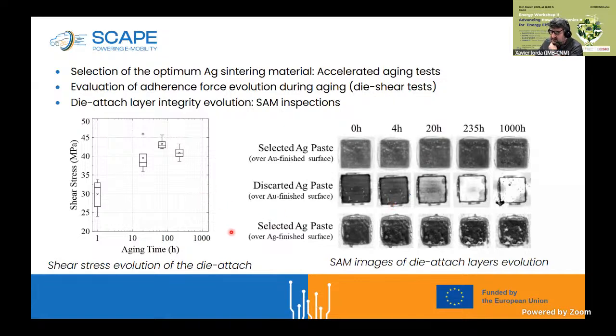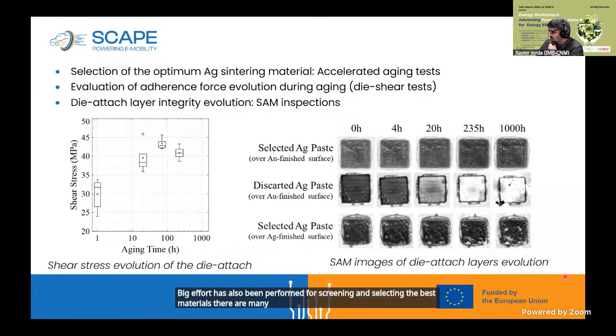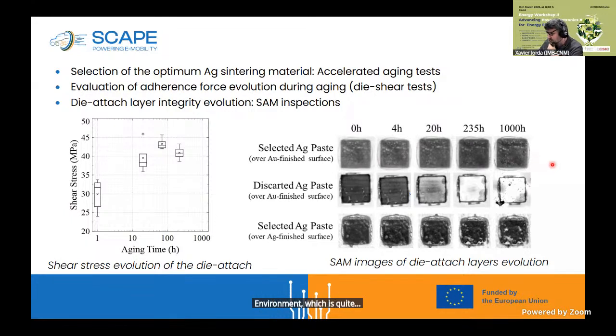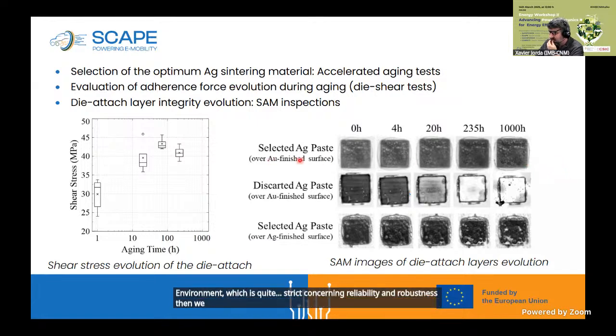A big effort has also been performed for screening and selecting the best materials. There are many possibilities at commercial level now, but we have selected the silver sintering materials that show the highest stability, because we are in fact in an automotive environment which is quite strict concerning reliability and robustness. Then we selected the materials which show the best stability during aging test.